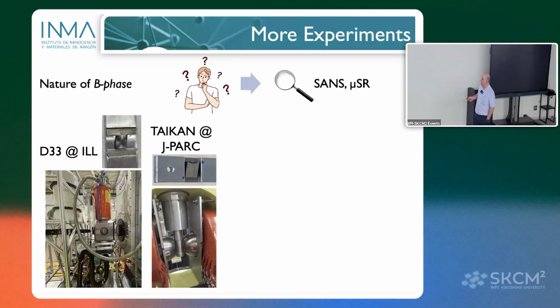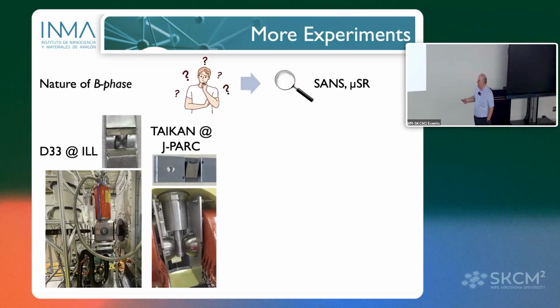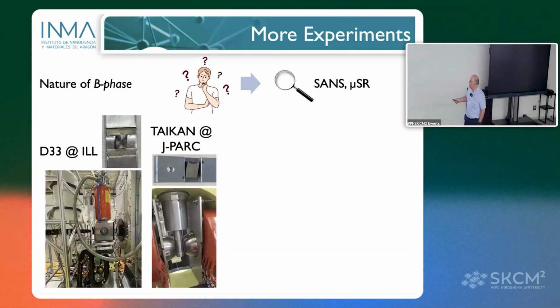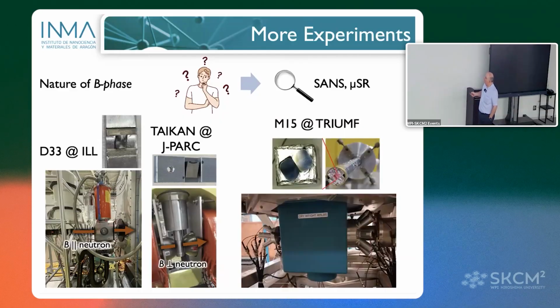We performed SANS experiments at the TAIKAN instrument in J-PARC, in MLF, which is a very good instrument, and also at ILL, at D33, which is also a very good instrument. Both are very good. Maybe for these experiments they are the best in the world. We used a very large single crystal fabricated by Kosaka-san. You can see here the single crystal, which is oriented. We know the orientations of the crystal, and we can go down in temperature and apply a magnetic field, parallel, perpendicular, etc., in order to do the experiments.